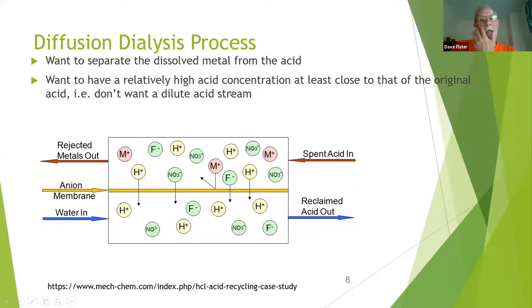Now, again, you have waste water coming out of the system, which has to go through treatment. Diffusion dialysis, again, an interesting process from the standpoint that now it's, again, a membrane. This membrane allows the hydrogen, nitrate, and fluorine, in this case, to go through the membrane. The metal ions cannot go through the membrane. So you have your spent acid coming in on this side. It's a counterflow system. Spent acid going in, coming out the other side is the metals that can't make it through the membrane. On this side of the membrane, you've got water going in, and now you have the osmosis pulling the hydrogen or the hydrofluoric and the nitric into the water stream, and now you've got your reclaimed acid going out. Now, again, this is a solution coming out that needs to be wastewater treated, high in metal ions.